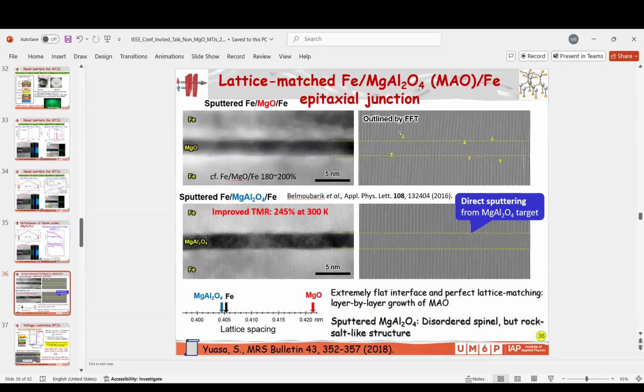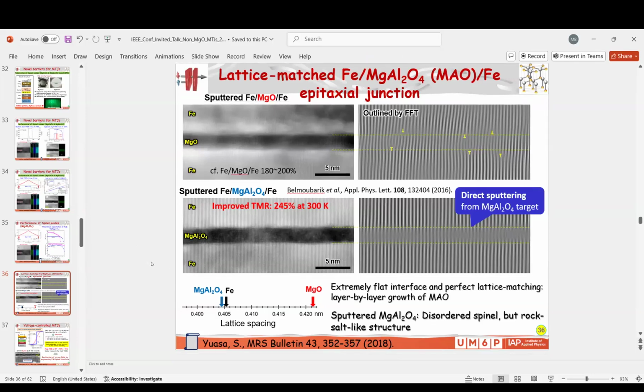So here we have some dislocations. You can see these yellow T marks. Then with the magnesium aluminum oxide, we have almost zero dislocations at the interfaces. It's not 100% perfect, but to be honest with you, the oxygen control, the oxygen density with MgO is much better, or easier to control, than with the spinels. This is maybe the weak point of the spinels.